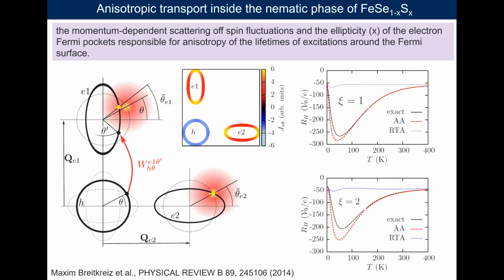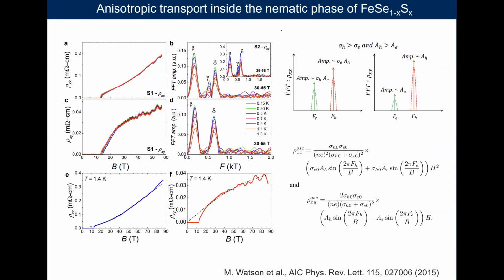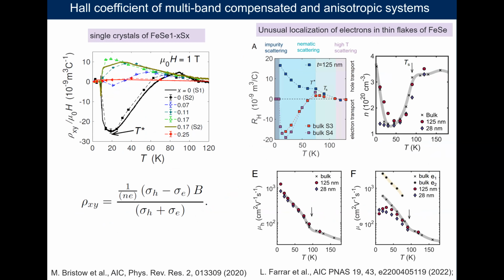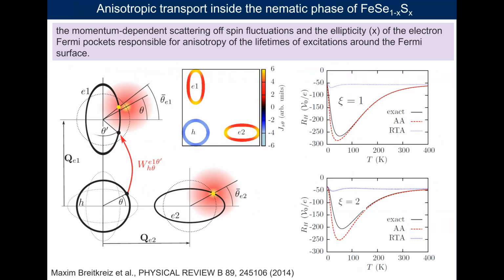Okay, so what we see is that the Hall coefficient becomes very unusual. In a way, it becomes negative in a regime where you only distort the Fermi surface. And your number of carriers in that regime seem to be lost. So in a nematic system where you only distort the Fermi surface, you should not have such a loss, which often occurs if you have a spin density wave transition, or you reconstruct the Fermi surface. So I think it's about how do we understand this unusual Hall behavior, Hall coefficient, in a nematic system.